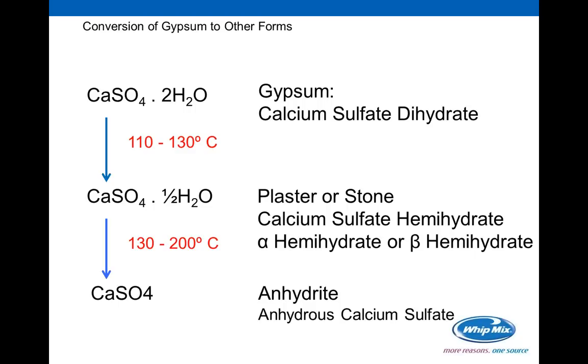Because of that, we go through a refining process. We don't do that here at WIPNET, and most of the companies that you purchase these materials from don't do it. We rely on companies like US Gypsum to do this raw product refining for us. They take that product out of the ground, mash it up in large bins and heat it. That heat process goes up somewhere between 110 and 130 degrees centigrade and drives the water off. Not all of it, but it takes off 1.5 waters, and it converts that molecule into what's called a hemihydrate, CaSO4 1/2 H2O. So it's lost 1.5 waters.